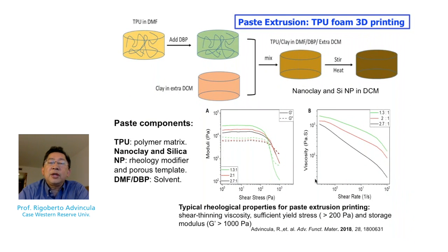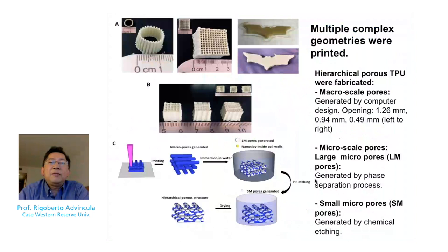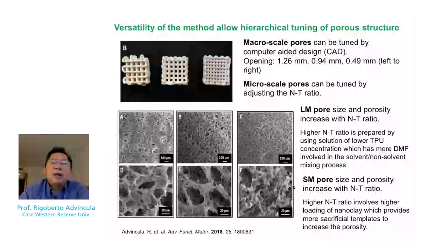So once we've converted the base into an extrudable printable material, we then 3D printed various shapes and sizes. In particular, we produced these grids that displayed various openings, and then finally we incorporated porosity through the nanoclay that was part of the formulation, and then removal of the nanoclay by hydrofluoric acid etching to reveal actually a porous material that was present on these 3D printed objects.